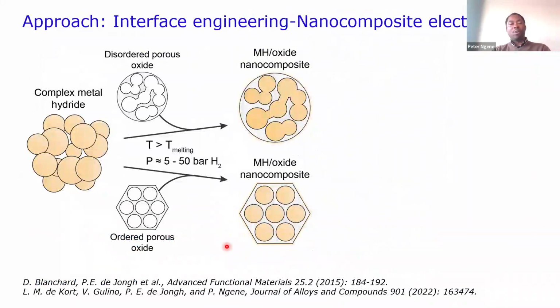So how do we make this nanocomposite? The same thing again that we did before. Basically, you have your complex hydride in this case. You have either disordered pores or ordered ones, and then you heat the sample, melt it, and it infiltrates all the pores, filling all the small pores. You can also do impregnation, but we prefer to do melt infiltration because it's much better. We don't have to deal with liquid in this case.